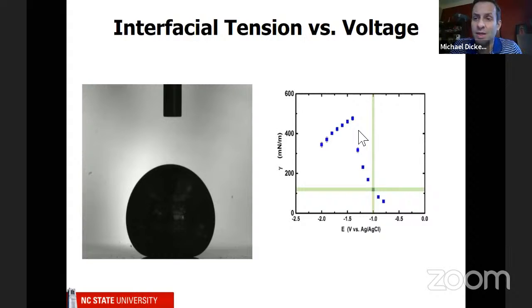But it suggests that, depending on how you make it, if you have the oxide layer, you could actually stabilize the metal. But the approaches that I've shown here, like sonication, those tend to be spheres. Now, some people have taken liquid metal and mixed it with silicone, a really viscous liquid. In that case, you can get what I call blobs, just non-spherical, kind of random shapes. What's difficult to do is to make sharp corners because of the surface tension. It doesn't like to be like this. It prefers to be rounded. And then of course, the smaller you get, the bigger the interfacial forces become. And so that's another challenge.